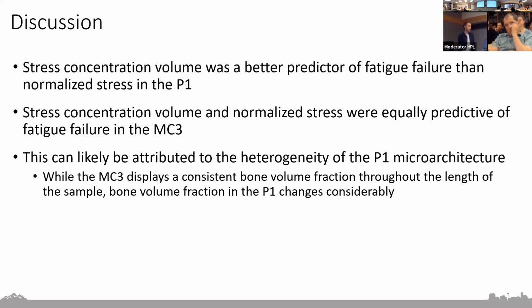So while the MC3 displayed a pretty consistent bone volume fraction throughout the sample, and pretty similar pore size throughout the sample, that's one reason why we might think normalized stress was representative of the stressing throughout the entire sample, whereas the P1 was much more heterogeneous compared to the MC3.